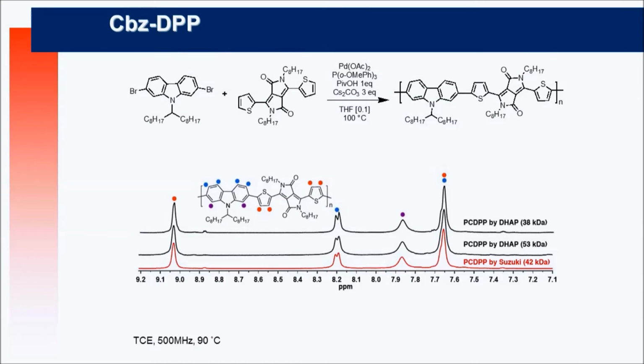We started with carbazole, and it's called DPP, diketopyrrolopyrrole, something. A very important polymer. A lot of CH bonds. Once again, if you compare with Suzuki, if you control the time of polymerization, you get different molecular weight and comparable NMR. So it's fully soluble, processable, comparable data. We sent those materials to Yuning Li here. It got even better, better hole mobility with those materials prepared by direct arylation.